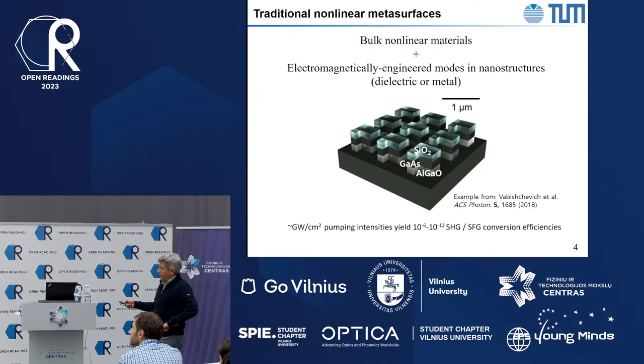Gallium arsenide is one of the highest nonlinear materials available in nature. And with this method, they're able to produce second harmonic generation, for example, from sub-wavelength films. Here the height is only of the order of a few hundred nanometers. But they still require very high intensities and have very low second harmonic output.